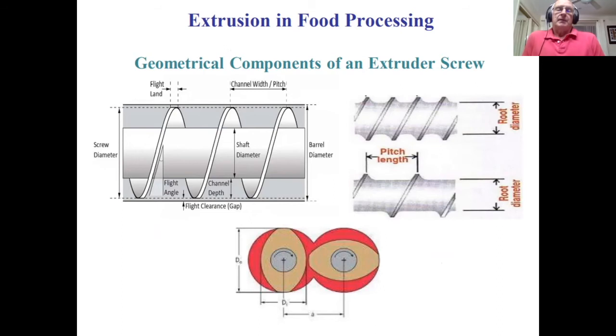There are a number of aspects of the screw geometry that we need to come to grips with. And first and foremost is the diameter. So usually if I refer to the diameter of an extruder, I'll be referring to the screw outer diameter. So it's just the tip to tip distance. The barrel diameter is always somewhat larger than that, thereby generating what's referred to as a flight clearance or gap. Now, this is the most important part of the extruder because this is where the shear is going to be generated. The frictional heat is generated within the confines of this narrow gap between the barrel wall and the high-speed rotating screw.